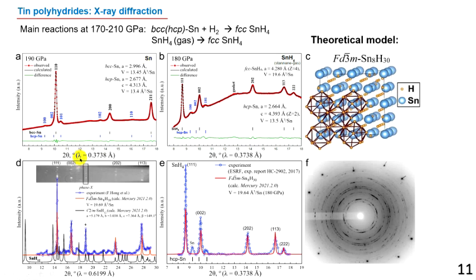On the panel A, you can see compression of pure tin. You see mostly it's BCC and a small impurity of hexagonal phase of tin. After that, we compress stannane. It's unstable gas. We load it in the diamond anvil cell, and after that compressed to 180 GPa. And you see the main product of compression is FCC SnH4 with the same hydrogen content as initial compound. This same product can be also synthesized using tin and molecular hydrogen loaded together, and as well we can do it by loading ammonia borane, and also the main product of the reaction is SnH4.